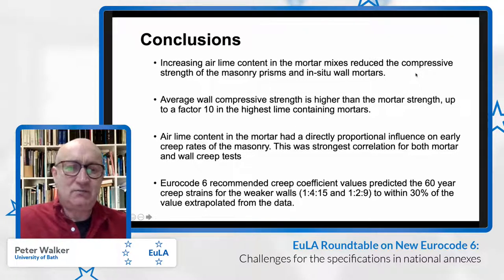I have not presented any of the work that we did on porosity testing or chemical characterization or SEM, but just looking primarily at the mechanical performance tests. So main points here: increasing the air lime content reduces the compressive strength of the masonry prisms and the mortars, as we would have expected, and in line with what's previously been reported. The average wall compressive strength is higher than the mortar strength, up to 10 times for the lower strength mortars. So in a sense, we see how the masonry units are important,